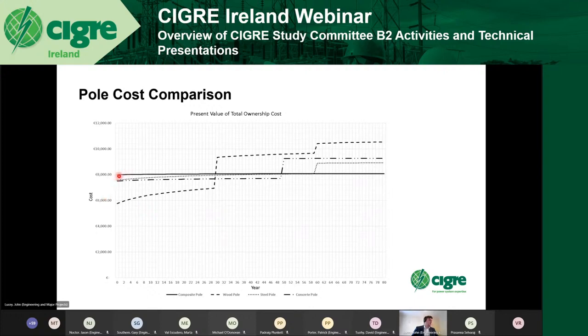So on this slide, you can see typically the composite pole, there isn't a massive amount of maintenance cost, and it lasts for about 80 years. Whereas with the wood pole, you can see the steps which occur at 30 years and 60 years in this example. Now, again, depending on the country, it could be 20 years, it could be 40 years, but in this example, 30 years was used. So you can see the steps where the pole needs to be replaced. Taking account of that, and also the slope in the line, which is where the maintenance cost comes in, you can see that ultimately over the 80 years, this example illustrates that a wood pole is more expensive than a composite pole.